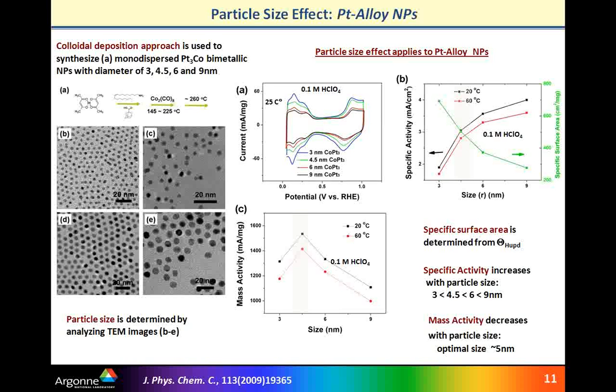And before we started the systematic approach towards nanoscale systems, something was lacking in the literature, and there is still, I would say, significant debate going on currently in society, whether the particle size effect is real or not. For that reason, our first attempt in characterization and electrochemical screening was to see whether the particle size effect applies for bimetallic systems. And here you can see that we used our colloidal solvothermal approach to tackle this issue, and we were able to synthesize particles between 3 nanometers and 9 nanometers. And then we made systematic electrochemical characterization.